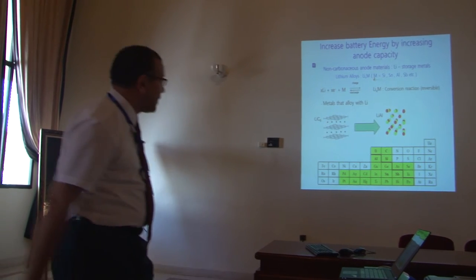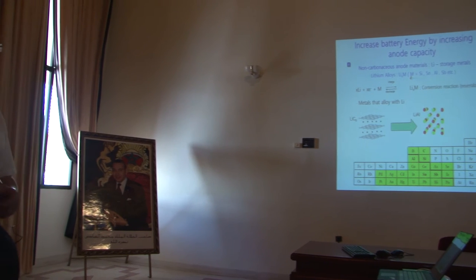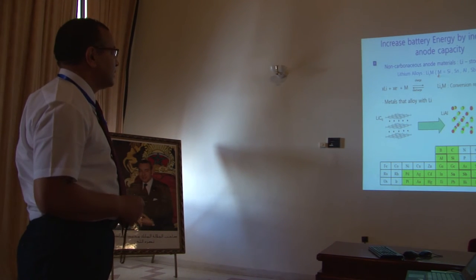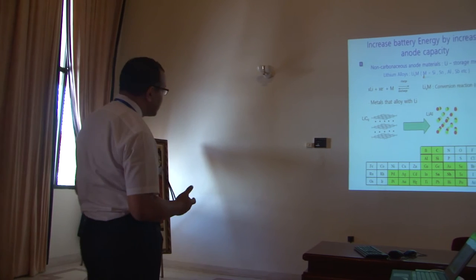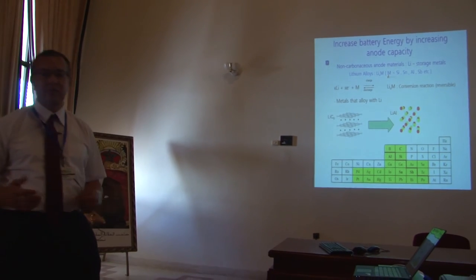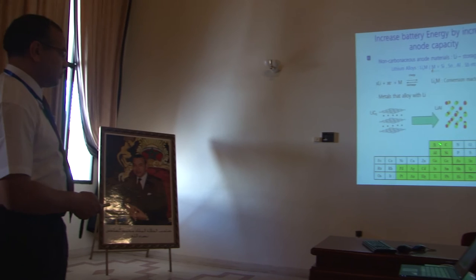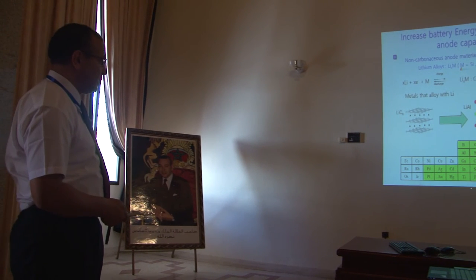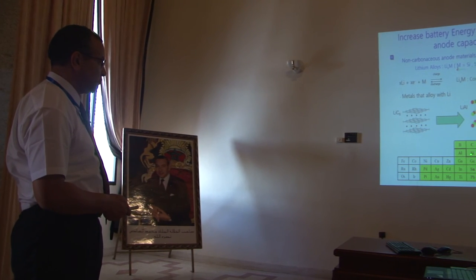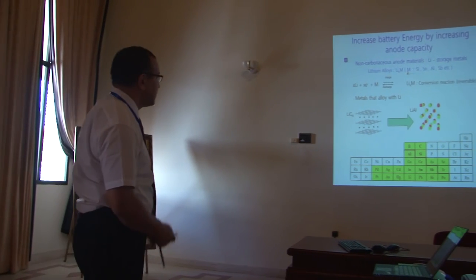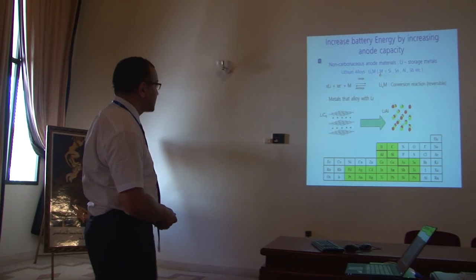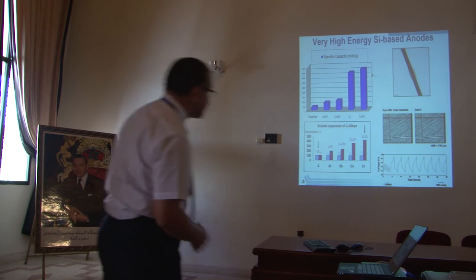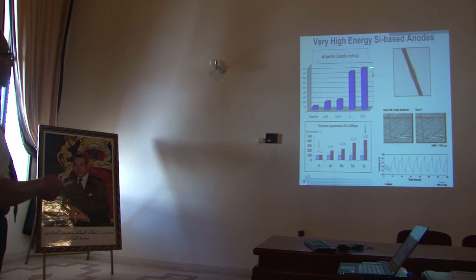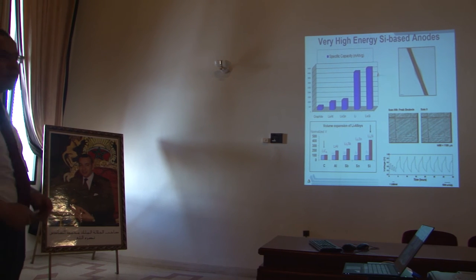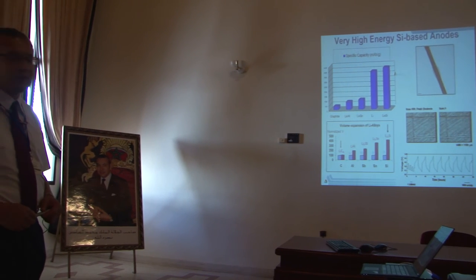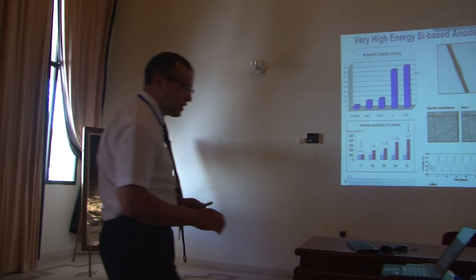Now, the last part, I'm going to skip this because the lady has already explained it. Most of the metal or metal oxide tend to alloy with lithium, and you can end up with significant capacities. For example, all these that are indicated in green can alloy. The ones of interest are tin and silicon, just because the cost of silicon is very low, and the capacities are very high. Unfortunately, even though we have capacities, the expansion is very significant. We're talking about 380%.